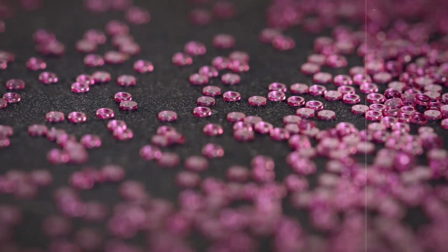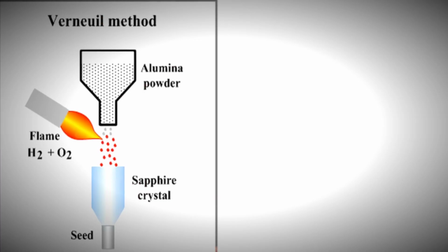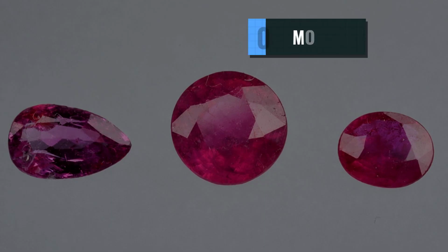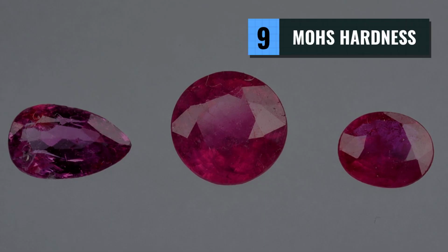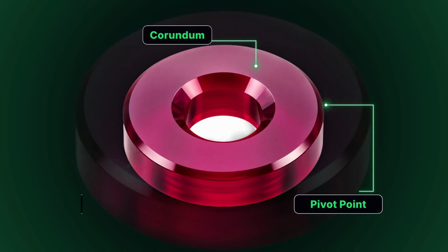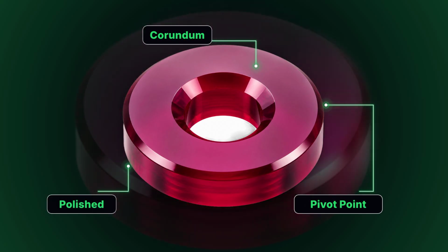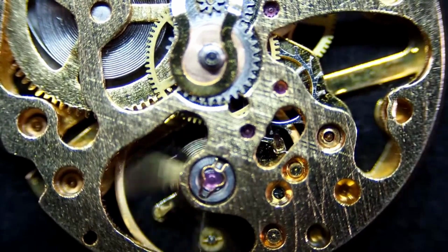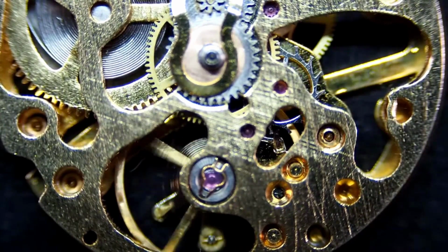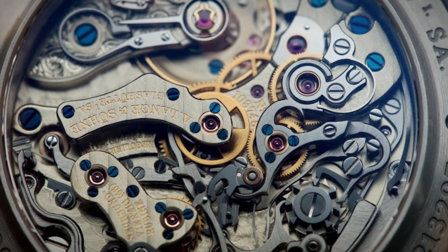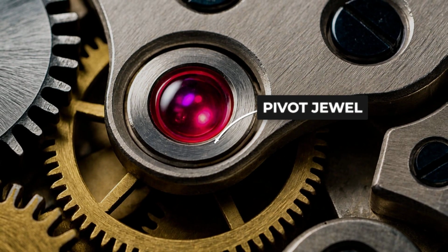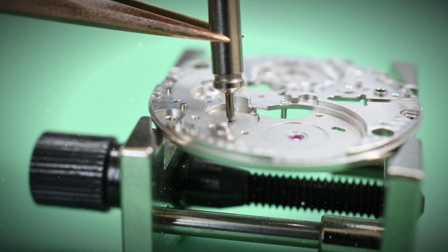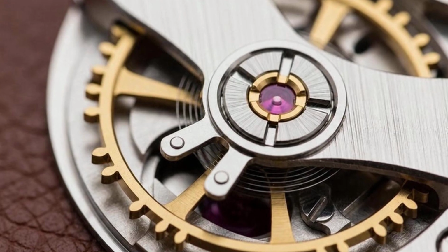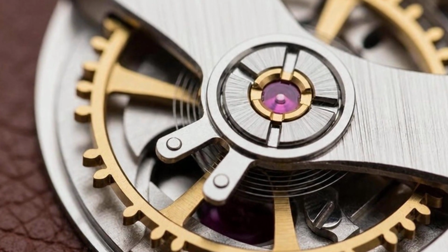The finished watch jewels succeed because synthetic ruby is chemically identical to natural corundum. Ranking at 9 on the Mohs hardness scale, this material is second only to diamond. This physical hardness, paired with a sub-microscopic polish, provides a nearly frictionless surface for rotating steel pivots. A standard mechanical watch movement uses approximately 17 of these tiny bearings, while highly complex movements require far more. Positioned at every high-wear contact point, these lab-grown gemstones protect the wheels and pinions, ensuring decades of continuous, high-precision timekeeping.